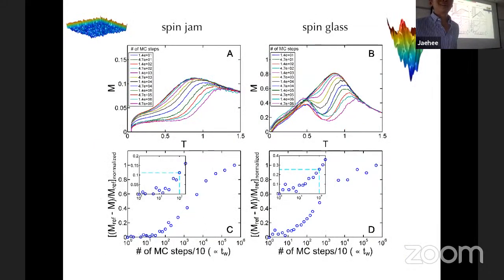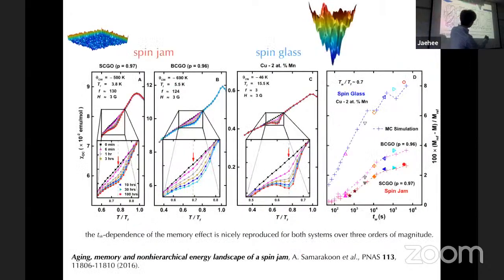Because there are people asking questions, yes, we can hear that. You can stop me whenever people ask questions. So then they also did this as a function of waiting time. And in their Monte Carlo simulation, we produced this slow aging for spin jam and fast aging in the spin glass case. In fact, these plus symbols are the calculations, and when we scale the same way, the simulation results reproduce the experimental data.